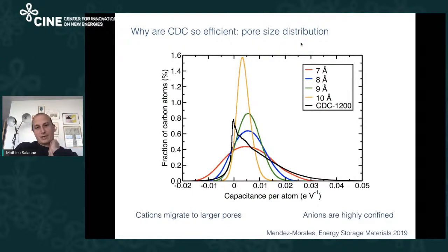If we compare this with a disordered carbon, you see that the black line here matches well with the red line at large values, but at low values, it matches better with the 10 angstrom case. What happens in the CDC, in this nanoporous carbon, is that you have a pore distribution. So you can have large capacitance in small pores, but also you have larger pores that allow you to accumulate anions and cations. Thanks to this, you don't have counter-ions going close to the surface, and so you don't have this problem of the negative charges as you have in the small pores of graphene.